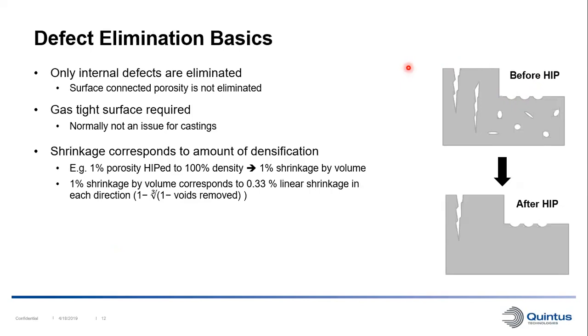The shrinkage we get in the process corresponds to the amount of densification we achieve. So if we, for example, have 1% porosity, and we hip a material and we HIP that to 100% density, we will get a shrinkage by volume of 1%. And 1% shrinkage by volume corresponds to 0.33% linear shrinkage in each direction of your part. So it's not a lot of shrinkage in the process.